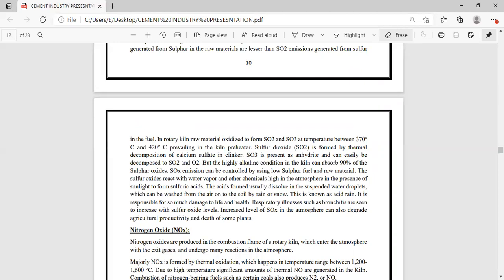Sulfur dioxide is formed by thermal decomposition of calcium sulfate in clinker, and sulfur trioxide is present as an anhydride and can easily be decomposed to sulfur dioxide and oxygen. But the highly alkaline conditions in the kiln can absorb 99% of the sulfur oxides. Sulfur oxides react with water vapor and other chemicals high in the atmosphere in the presence of sunlight to form sulfuric acid. These acids usually dissolve in suspended water droplets, which can be washed from the air onto the soil by rain or snow. This is known as acid rain.